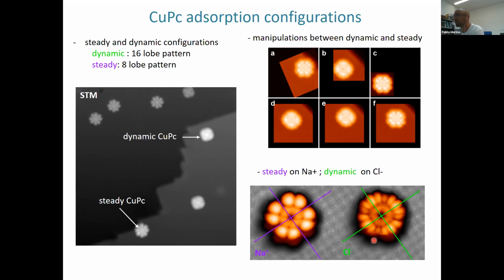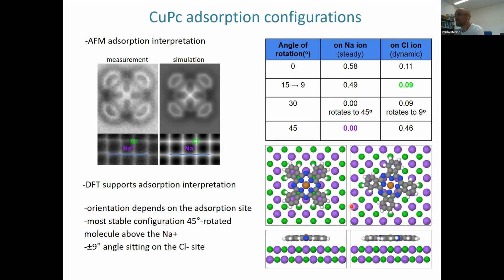Okay? And actually, we don't only have SPM, but we also have AFM data, which further corroborates our interpretation. In this AFM image, we did a single image at 2 different tip heights. In the lower part, we were resolving the salt layer, and on the upper part, the molecule, and one can immediately see that the steady molecules are sitting on sodium.